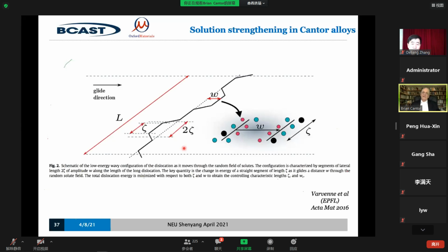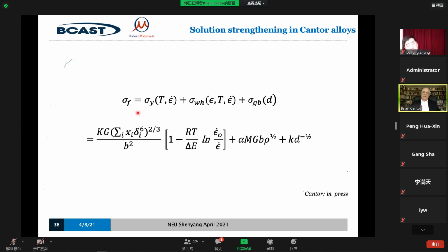And that's what makes the Cantor alloy much stronger than a single component FCC material or a simple 2-component solid solution single phase FCC. And overall, the flow stress, that's not French stress, that's flow stress, is given by a sum of 3 components. There is the basic yield strength at large grain size, that's this component, together with a work hardening component.